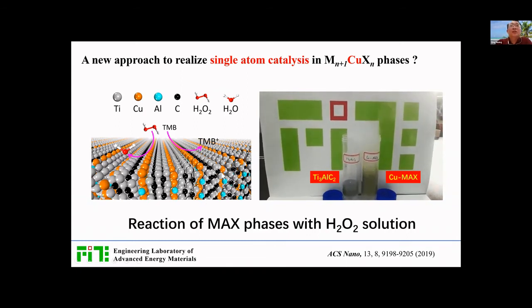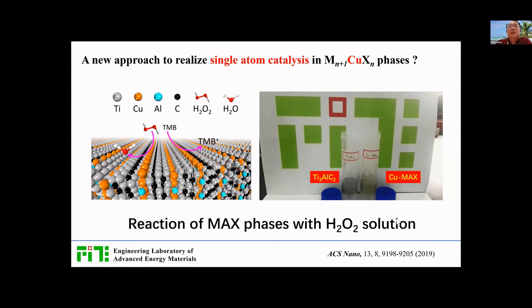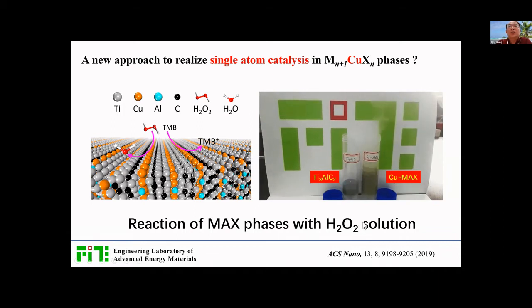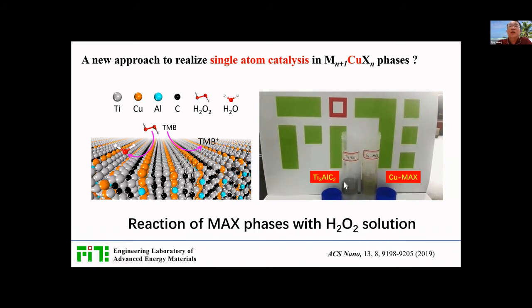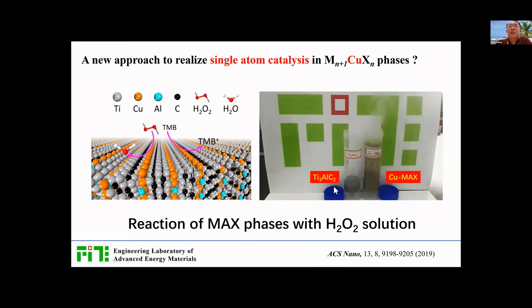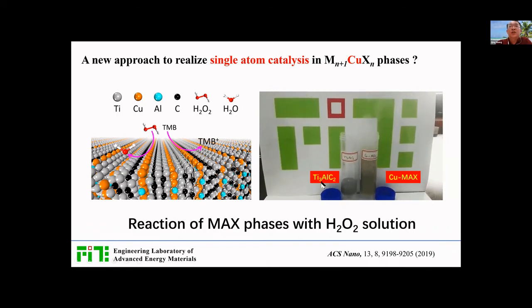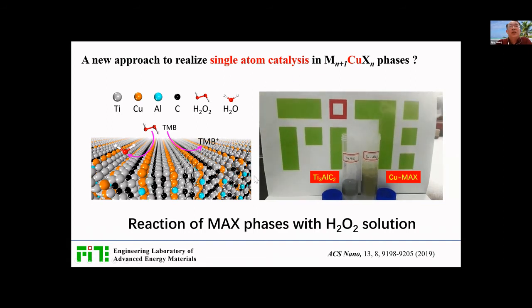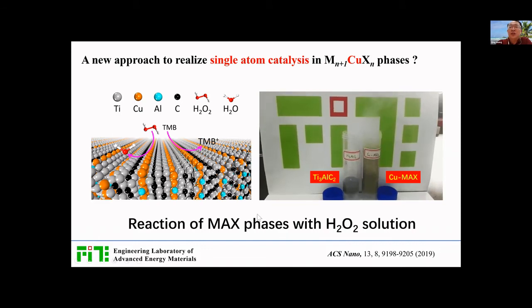Here I show that if we put these MAX phase powders into peroxide solutions, the copper MAX phases may act as a catalyst to decompose the peroxide into oxygen. But if you use the traditional MAX phases, there's no such reaction. So it can be a single atom catalyst in our new MAX phases. I think there should be more chemical study of these new materials.